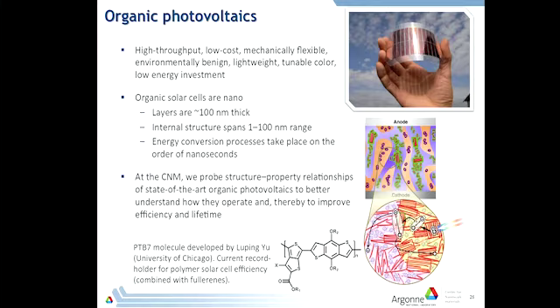And even beyond that, within those layers, there's a very complex hierarchical structure. And what I mean by that is, it's ordered at all different length scales. If you home in on the very, very finest length scale, here you've got the molecules, but those molecules arrange themselves into little domains, and then the domains of different types of molecules arrange themselves on a rather larger scale. And here you've got the two different types of domains. And if we look at what happens within those domains, the way a solar cell works, light comes in, it generates a pair of charges, one positive, one negative, and then they have to flow and eventually reach the anode and the cathode. Well, if we've got this nice material that's interdigitated, the charges don't have to flow so far, and that makes the material very efficient. And so in that way, we can start to help overcome this problem of the high expense and low efficiency of solar cells.